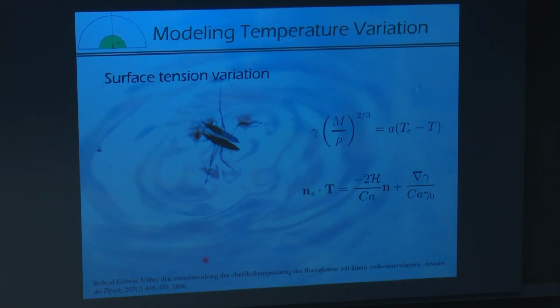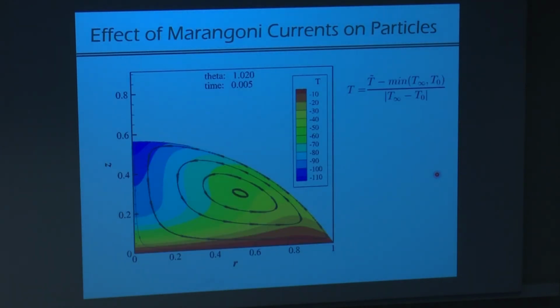So we also have to take into account that the surface tension now will change because it's a function of temperature, and we use this equation to describe surface tension as a function of temperature. And also the traction boundary condition, no longer do you just have this term, you have to add the gradient of the surface tension because the surface tension is changing along the interface. So when you do that, you get this Marangoni flow that's shown here.